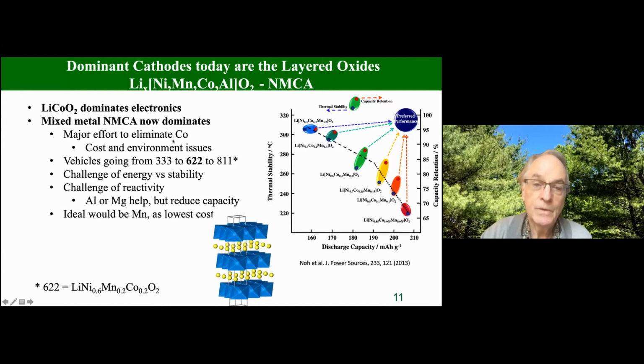There's a major effort to get rid of cobalt, and as Jeff showed, it's not really necessary. This is driven commercially, mostly by cost. So going from 333 to 622 cut the cost of the cathode material by 40%. And then obviously you've solved some of the environmental and child labor issues. So this is a classical plot now from Sun's group in South Korea. I think everybody knows this. The less nickel you have, the more stable the material. The more nickel you have, the less stable, but the more nickel you have, the higher the capacity. And also the capacity retention is worse with the high nickel, just because you're going to tend to go to a higher voltage. So this is one of the challenges.